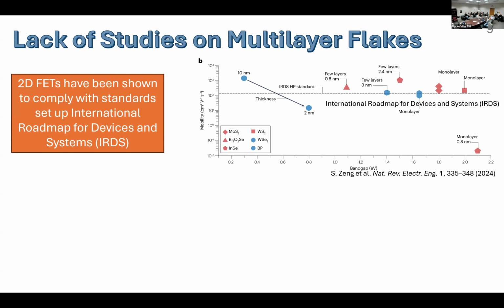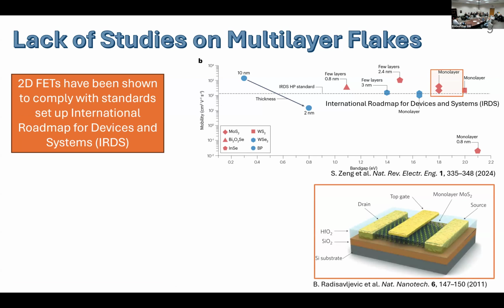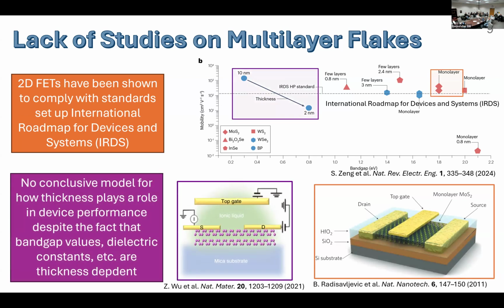However, as you can see here, most of these are focused on a couple materials, and they're also focused on monolayer or few layer flakes. Despite the fact that, as you can see from this figure here, if you look at a 10 nanometer black phosphorus field effect transistor compared to a 2 nanometer one, you would have a higher mobility. So this has prompted the interest in discovering multi-layer flakes and how thickness plays a role in device parameters.